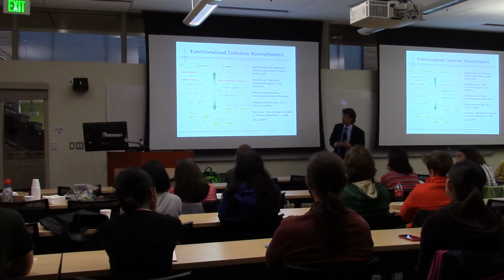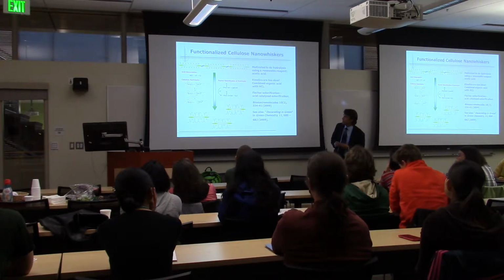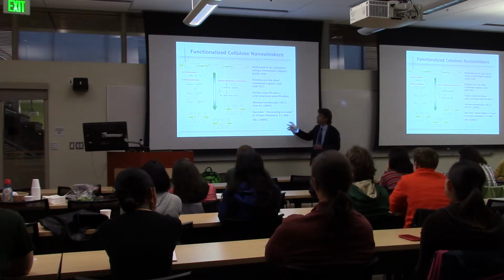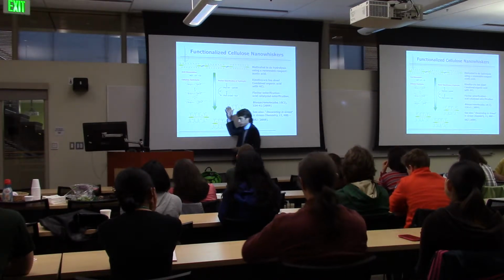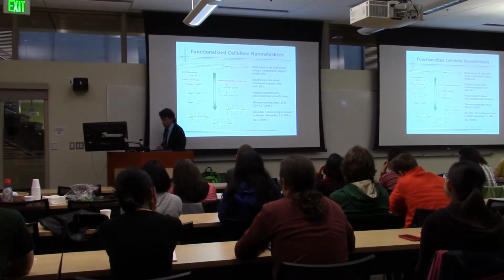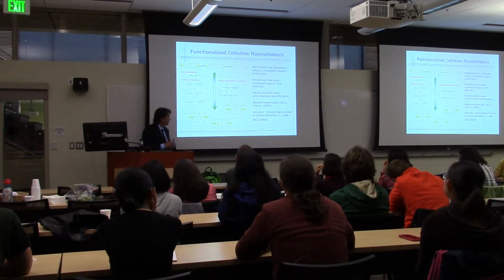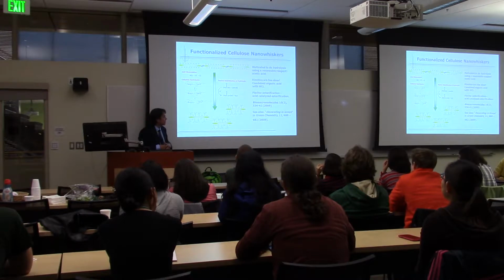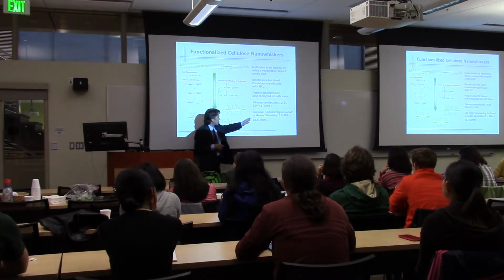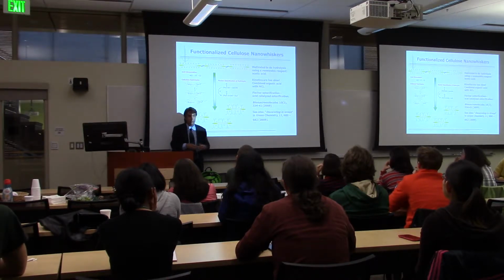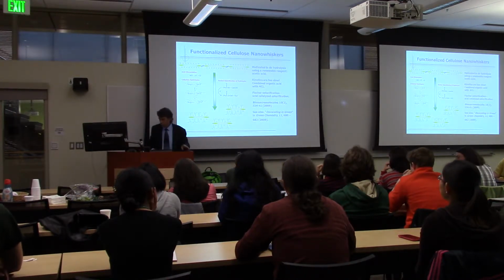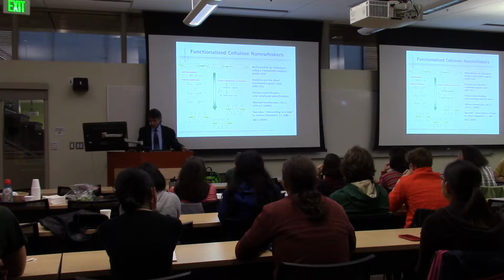Yes, we do it with lactic acid, in fact. And I'll show some examples of that later. So the nice part of this, and we've also practiced this chemistry, is that it is a much greener chemistry than the way typically people functionalize carbon nanostructures. So in this green chemistry paper, we do this both on cellulose, but also on carbon nanotubes and buckyballs as well.